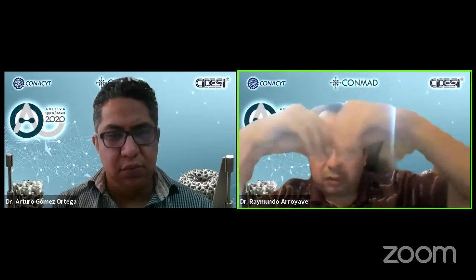So we haven't done this for 4D printing, but we are doing this with DED, with multi-material printing. We can do that, and actually, we have a setup in our lab, in the lab of a collaborator, that we call the Rapid Alloy Prototyper. So we can use a multi-material printer to print different alloys in a single plate. Then we can do high throughput characterization of those alloys. So we're going to try to do alloy development. So it is possible to do local alloying with elemental powders, but we have done that only with our DED